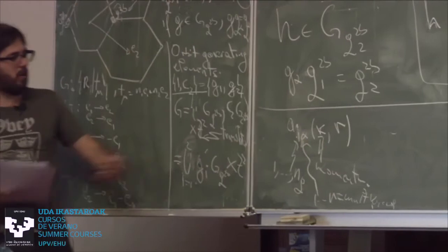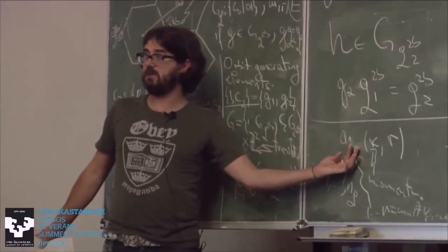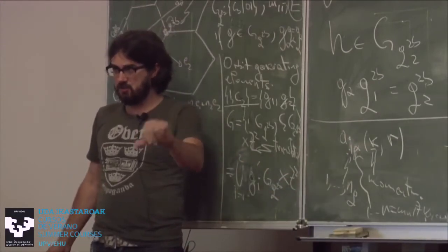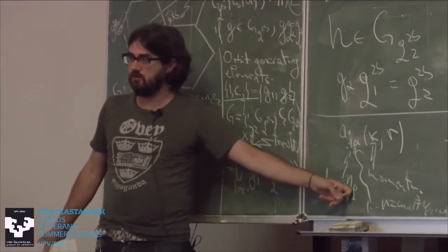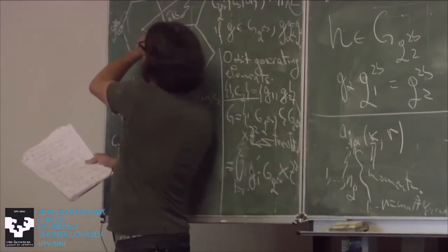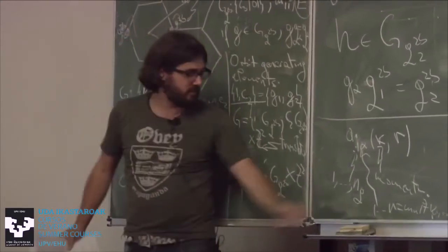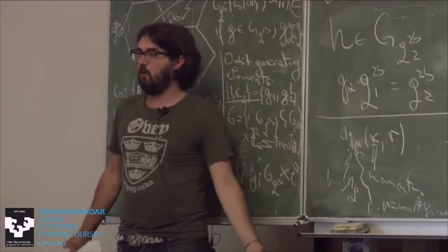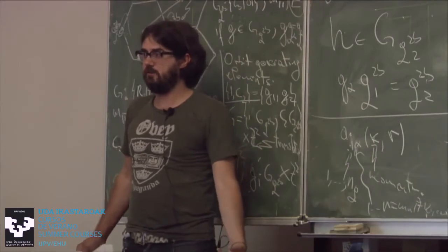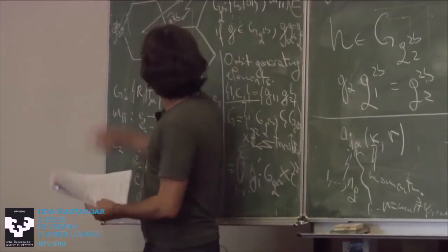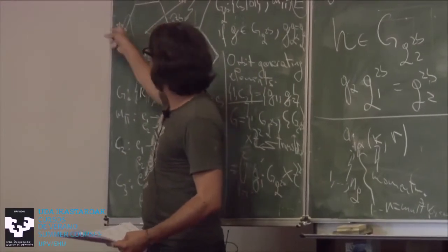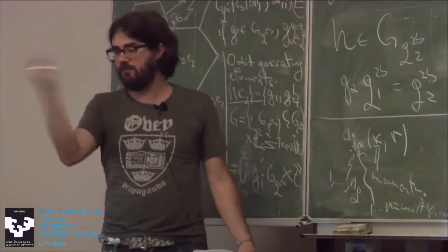So, what would be this matrix in terms of i alpha for pz orbitals, spinful pz orbitals in graphene? Well, spinful pz orbitals have 2, spin up and down, so this goes from 1 to 2. But they also sit at 2b, so they have 2 Wyckoff positions, this and this one. So this runs from 1 to 2 also. So the basis state would be a 4-dimensional vector, and I'll show you the band representation is 4-dimensional. In other words, I have pz orbitals here, up, down, pz orbitals here, up, down, a 2-dimensional representation plus a 2-dimensional representation, 4-dimensional representation total. I'll have 4 bands that connect through the Brillouin zone.